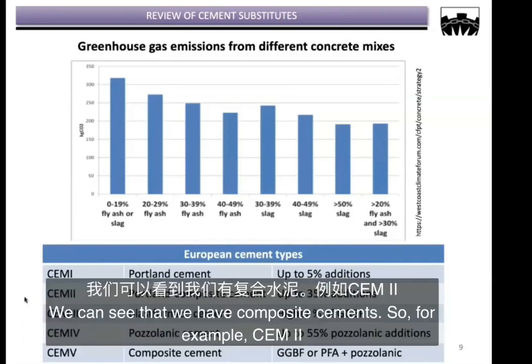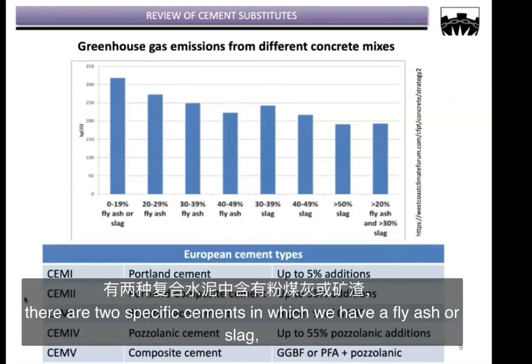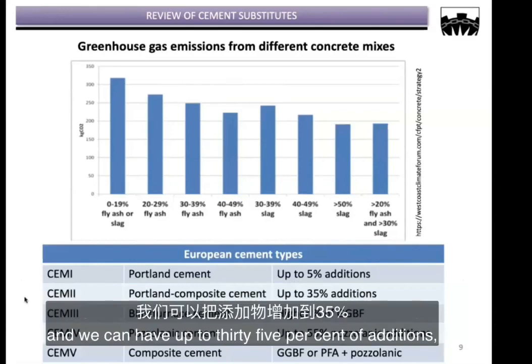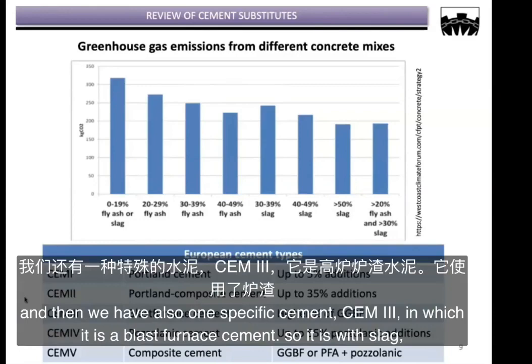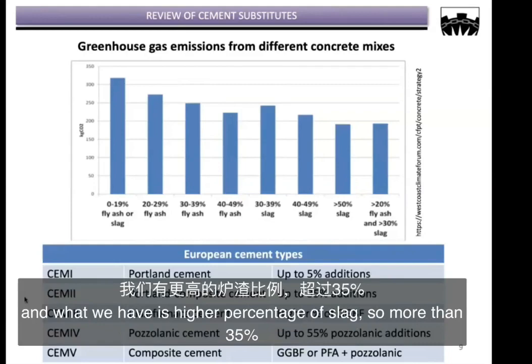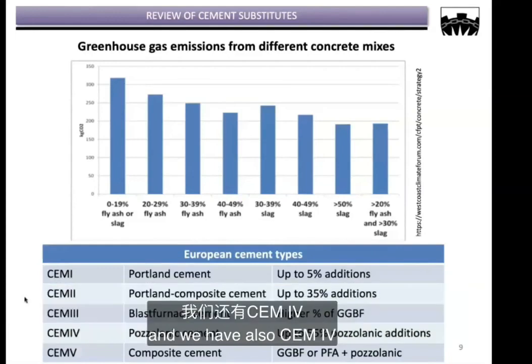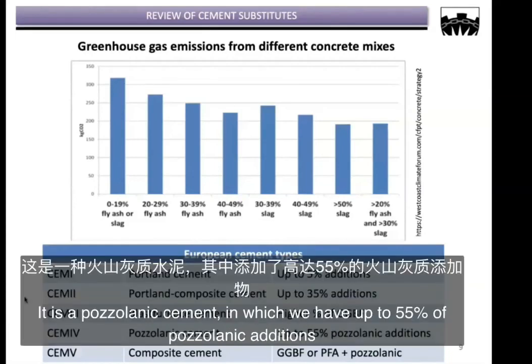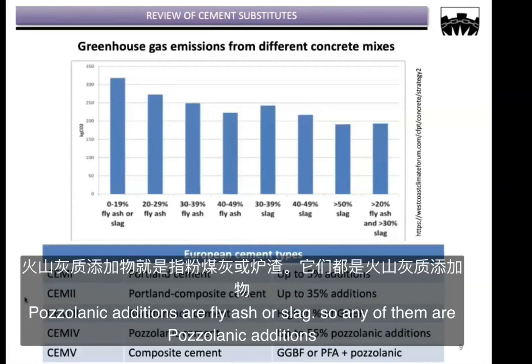We can see that we have composite cements. For example, CEM2, there are two specific cements in which we have fly ash or slag, right? And we can have up to 35% of additions. And then we have also one specific CEM3, which is a blast furnace cement, so it is with slag. And we have a higher proportion of this slag, more than 35%. And we have also a CEM4, which is a pozzolanic cement, in which we have up to 55% of pozzolanic additions. Pozzolanic additions are fly ash or slag. So any of them are pozzolanic additions.